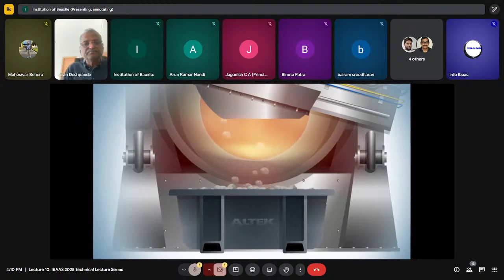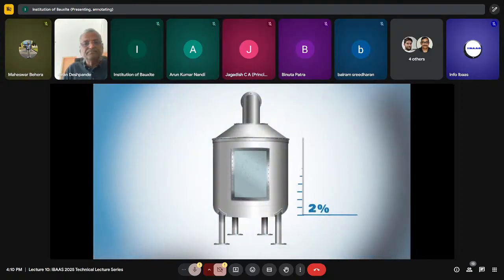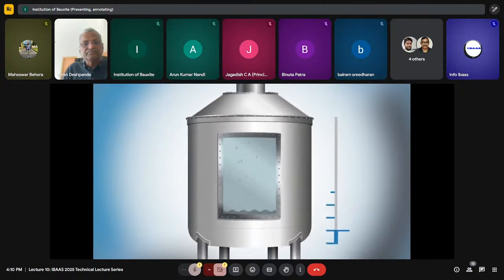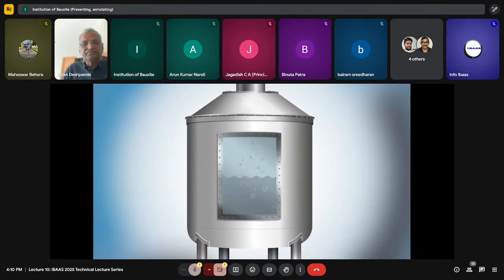The salt slag, the residue that remains, is tipped into salt slag bins, where it is cooled rapidly to preserve any remaining aluminium units. The cooled salt slag is then transferred to the alusalt process, where it's mechanically crushed and the last remaining aluminium is recovered. The remaining slag is mixed with water until the salts present are dissolved.